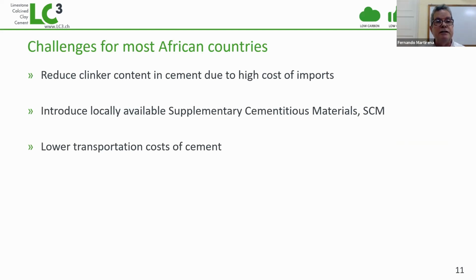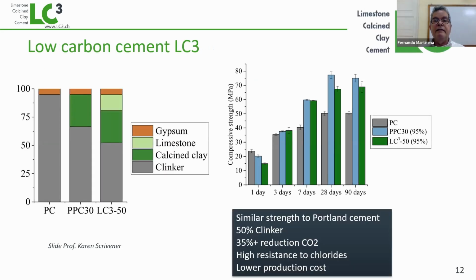So the challenges for most African countries are, first of all, to reduce clinker content in cement due to the high cost of imports, but also due to environmental reasons, if you want to really reduce carbon emissions. And to do so, you have to find locally available supplementary cementitious materials. In this regard, I want to make the case that calcined clay would be a very interesting material for Africa, which would also have the impact of reducing transportation, because you can set the plant near the source of the supplementary cementitious material. And this is where the limestone calcined clay cement plays a role.